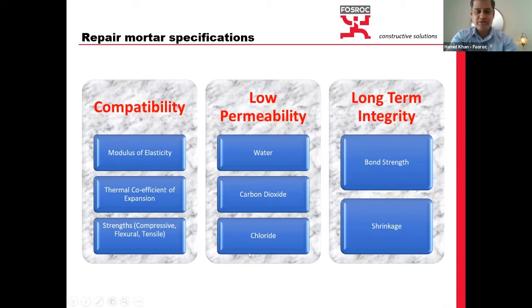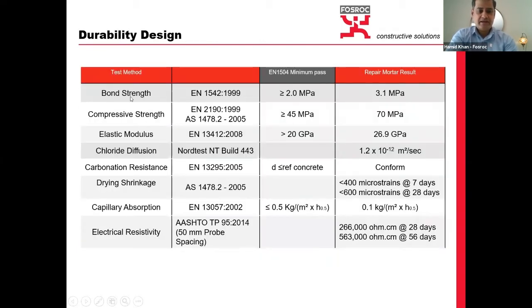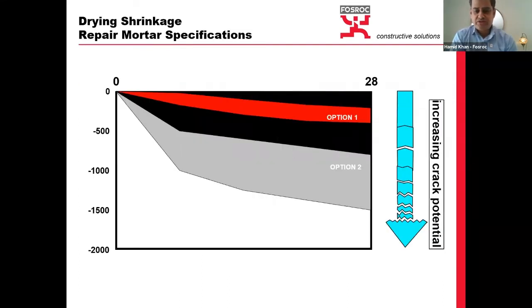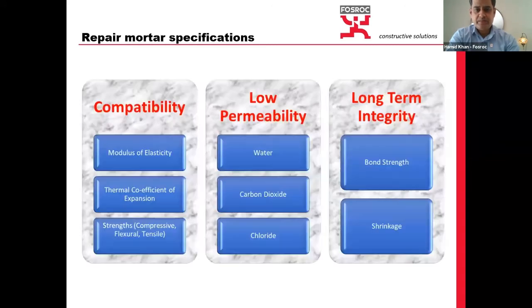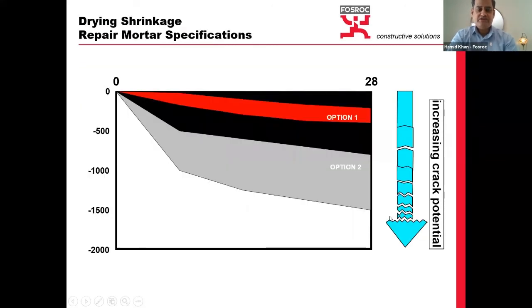So how could we go wrong with not qualifying for the low permeability? And the same is with bond strength, for example, and elastic modulus and so on. If I talk about shrinkage, which is part of the long-term integrity here, the shrinkage of repair mortars, I was reading a research paper that says that it is one of the most important parameters during the selection of repair mortars. I've seen that repair mortar data sheets sometimes don't mention the drying shrinkage properties on the technical data sheets. I believe they should be mentioned clearly and loudly.